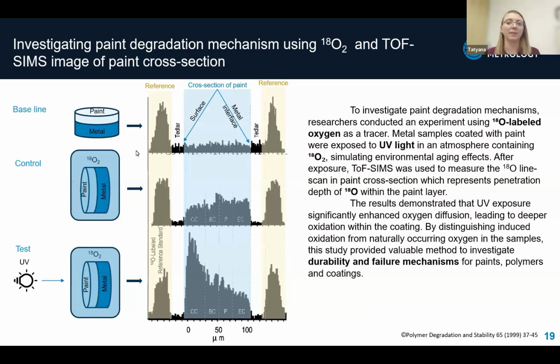This experiment is in some way a continuation of the previous one. This is a classic use of isotopes for mechanism investigation and clever use of ToF-SIMS for its measurement. To investigate paint degradation mechanism, the researchers conducted an experiment using O18 labeled oxygen as a tracer. Metal samples coated with paint were exposed to UV light in an atmosphere containing O18, simulating environmental aging effect.